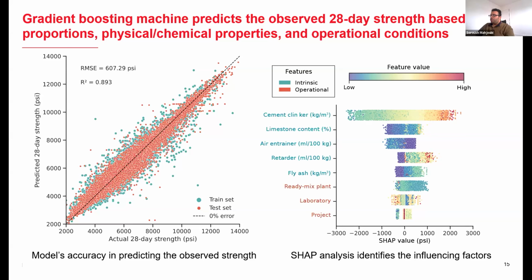But we have also considered the operational features, as I mentioned, such as the ready-mix plants, laboratory, and projects. And these variables have a significant influence on the predictions as well. For example, the ready-mix plant can increase or decrease the compressive strength by over 1000 psi, and this shows the variations in handling and mixing in the ready-mix plants. And by standardizing these procedures, we can actually have some GHG gains, and we can reduce the GHG by improving the quality control in the ready-mix plants. The same applies to the laboratories. We can see that the laboratory has an impact on the compressive strength too, and this leads to a reduction or improvement in the compressive strength.